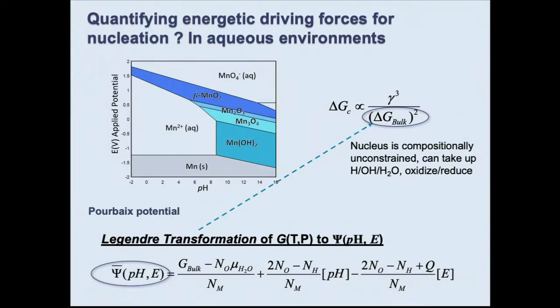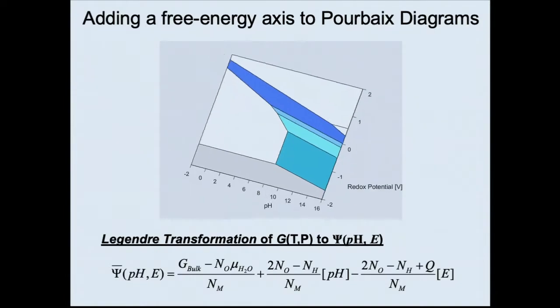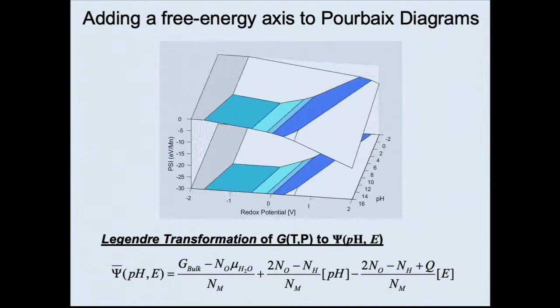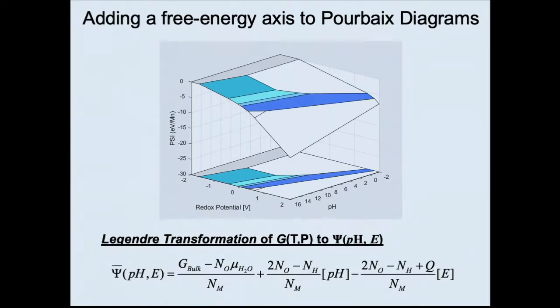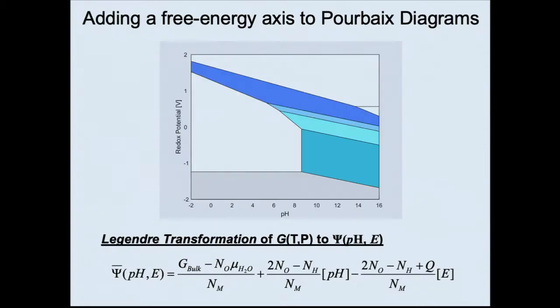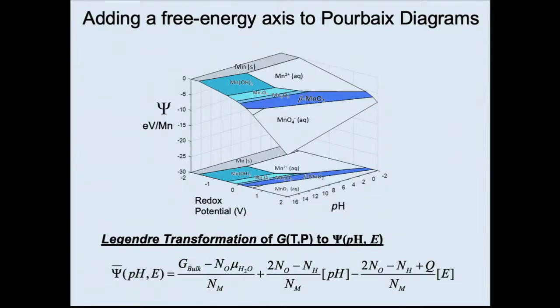You have to take the Legendre transform of the Gibbs free energy, and that looks really complicated, but really what matters is your Legendre transform with respect to the chemical potential of water, the pH, and some potential, which is again the cost of your electrons, to do oxidation reduction. If you do that, you can do really cool stuff, and you can put this on some kind of map. So this is again the phase diagram, but now you can actually put an energy on it, which is the equivalent of free energy.